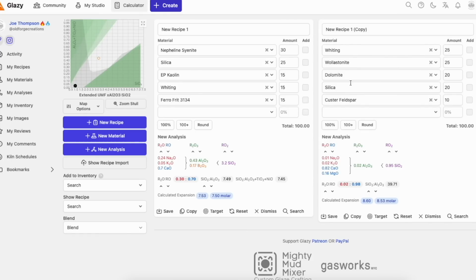Once you put the silica in proportion to the flux, turns out, I've never seen a flux ratio like that before. You're aiming for 0.3 to 0.7 is pretty good. Around 30% from your sodium and potassium, and around 70% from calcium, magnesium, that lot. In this particular one, we've got so little feldspar and so much of the 3 calcium sources that we're up to 0.02 and 0.98. Never seen that in a glaze before. I will make that and apply it to a pot and we will see what that does.